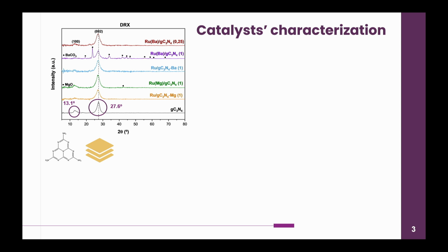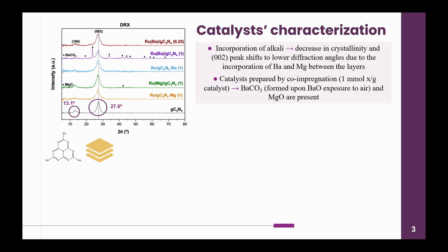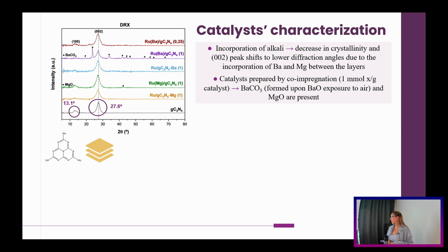Both peaks are maintained in every catalyst, but with the incorporation of the alkali metal, we can see a decrease in crystallinity, and also that the first peak is shifted to lower diffraction angles, which may be due to the incorporation of barium or magnesium in between the layers of the C3N4. Also, in the catalyst prepared by co-impregnation, we see the presence of barium carbonate and magnesium oxide, phases that we don't see in the catalyst prepared by mixing the alkali and the urea before the thermal polymerization.